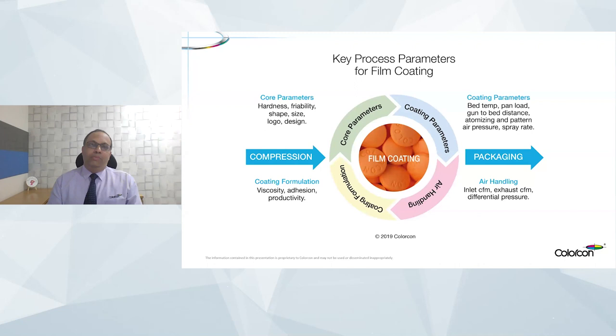This is similar to the previous slide, where from a core parameter perspective, the size of the tablet, its friability, the design and shape, the logo design, the placement of the logo, and of course the film coating formulation itself matter. You have heard of different types of Opadry families, coming with different solids content based on the composition, different viscosities and productivities. And then when you come to the process parameters, of course the pan load, bed temperatures, atomizing pressures, CFM, different types of temperatures, all play a role. Basically, the tablets have to undergo a lot of processes, and we need to withstand all of these together in the coating equipment before coming out with the perfect finish.